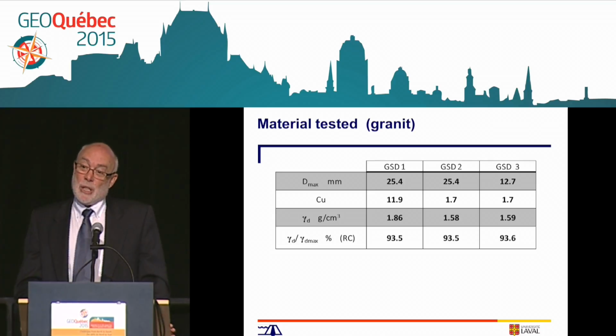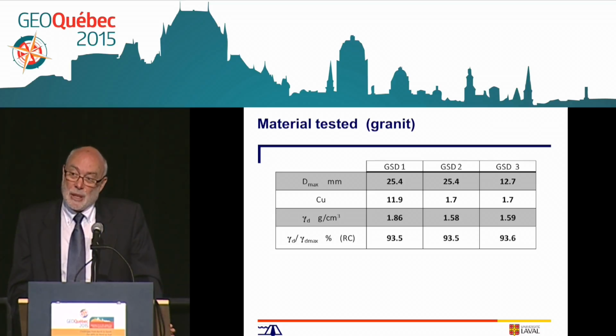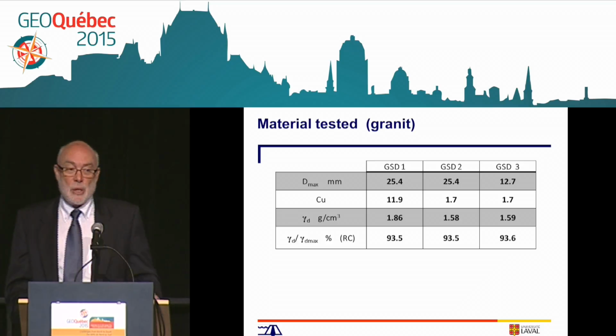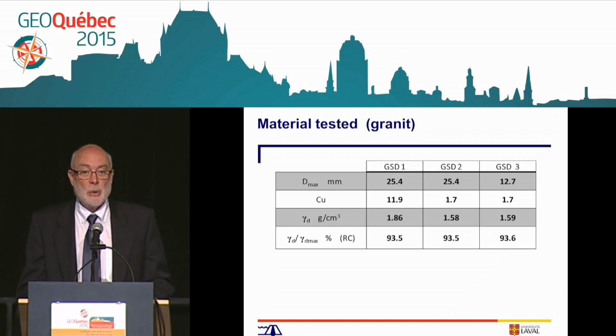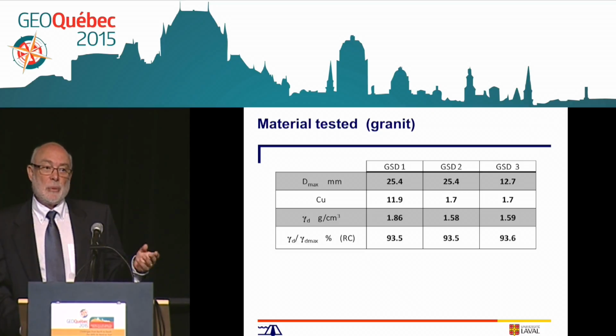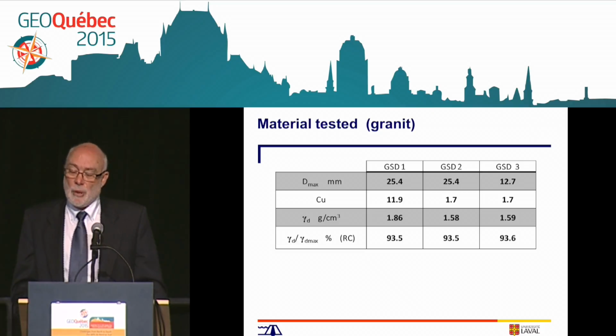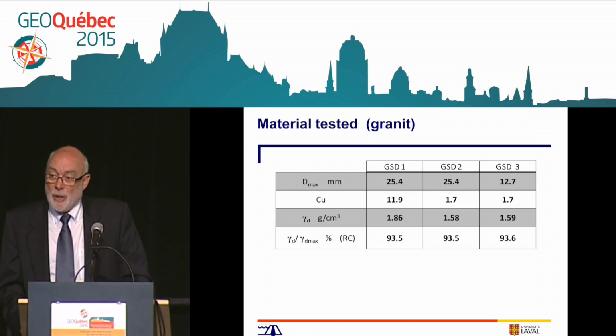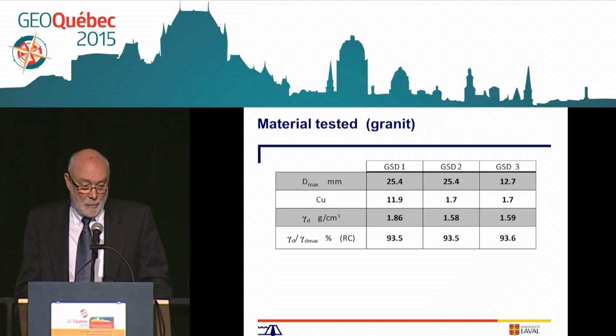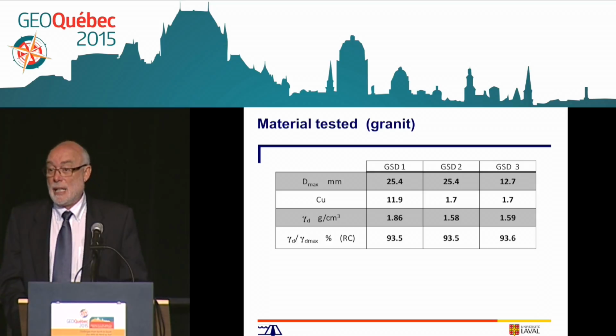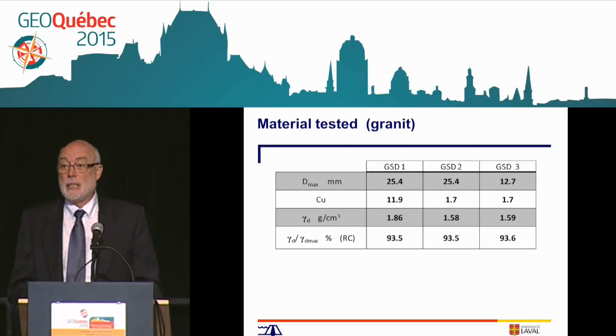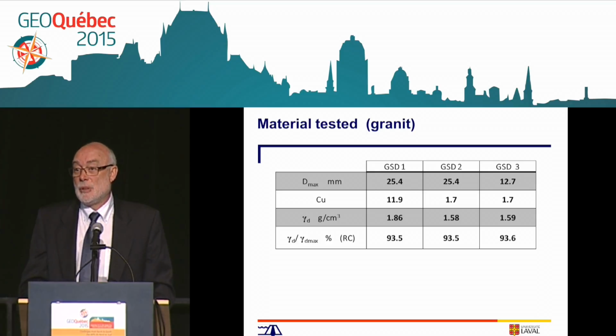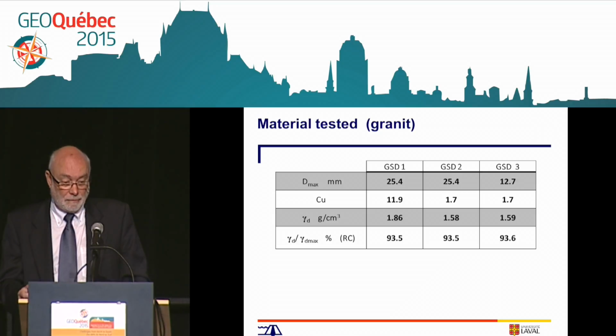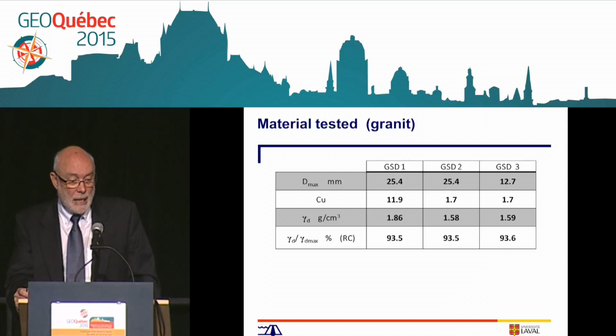But this time, we changed our conditions. We did not study the density effect. We knew that now. We said we do the same relative compaction. Often in dam engineering, we like to work with relative compaction. So it was about 93%. And we changed the grain size distribution and the maximum grain size, to see if there is a scale effect. So we have three grain size distributions, 1, 2, and 3.